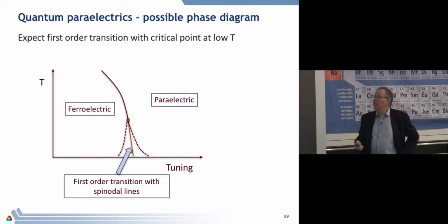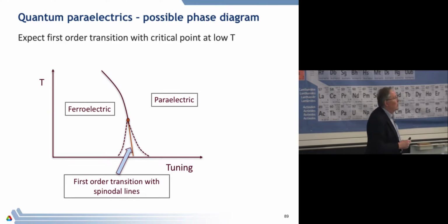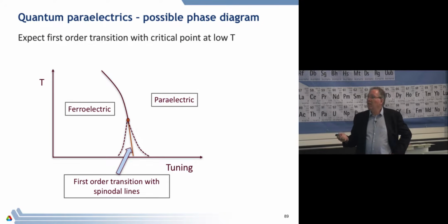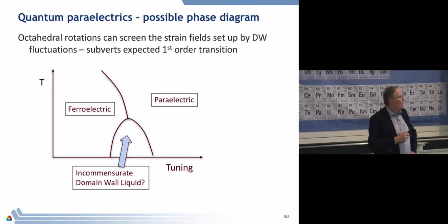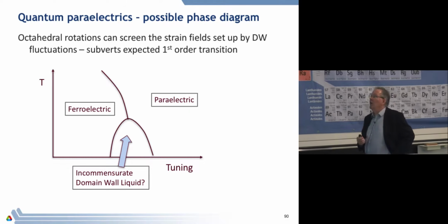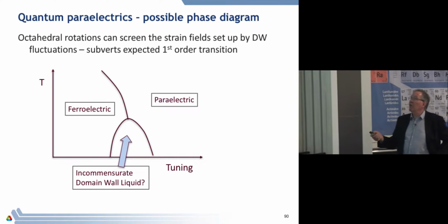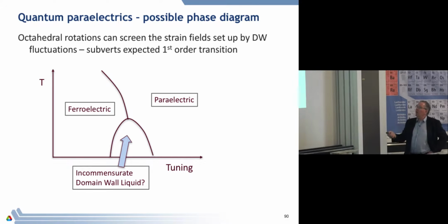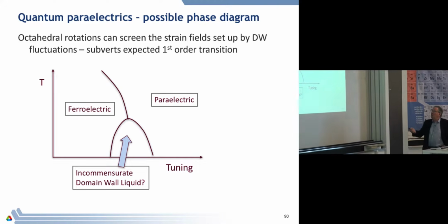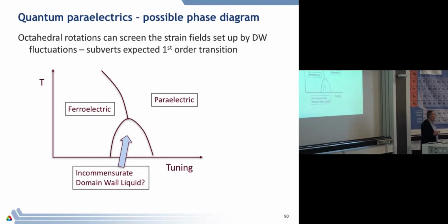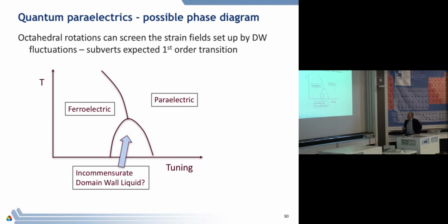I'll leave you with a last speculation, actually, that quantum fluctuations make this into an incommensurate domain wall liquid. And it will be nice to know whether you can do this, because these fluctuations from ferroelectric to paraelectric this way can be driven by temperature, and in principle they can also be driven by quantum mechanics. This might solve a number of puzzling conundra about a very enigmatic material, strontium titanate.